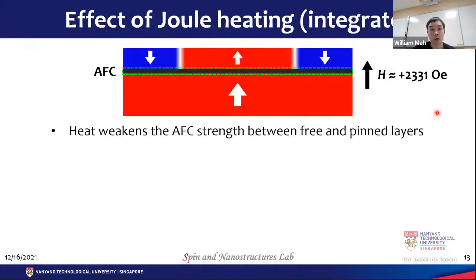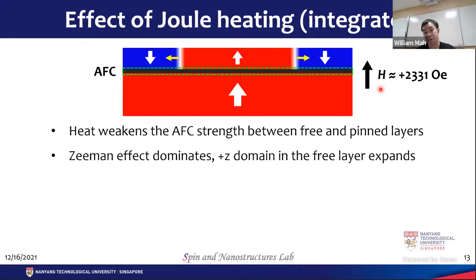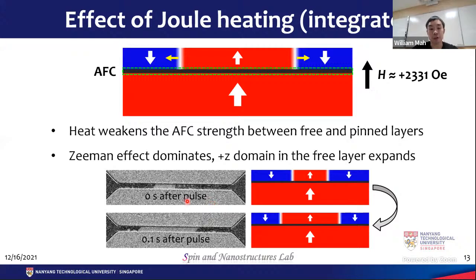And so the idea of how heat can push the domain wall is, first, it weakens the antiferromagnetic coupling between the top and the bottom layers. But at the same time, I'm still applying a field in a plus Z direction because I want to nucleate the domain walls. So the antiferromagnetic coupling strength is weakening, but the whole time the field is still there. So the Zeeman effect would dominate, and in that case, my domain would expand. That would push the domain walls away, which is what we observe in the videos and also in the screenshots.